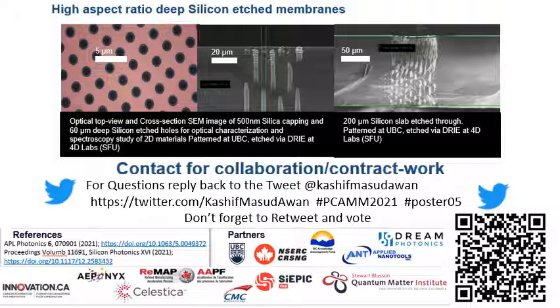A second kind of membrane was a bit more challenging because this was through etched. So this is a 200 micron thick silicon wafer, and we are etching through. So 200 micron through, and we are etching hole sizes down to 5 to 10 micron in diameter. So again, this was also done successfully, and again we used the Heidelberg to pattern and the DRIE at Simon Fraser lab for the deep etching.